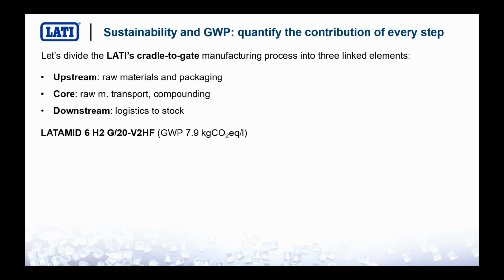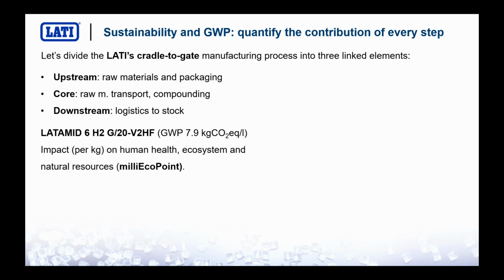What we have found is that for a material like this one, a nylon 6 with 20% glass and halogen-free flame retardant, having a global warming potential of 7.9 kilograms of CO2 equivalent per kilogram, it is possible to evaluate the impact of every kg of this material on human health using a very specific system called Ecopoint, whose definition is the one you see here below: the environmental impact of every European citizen.